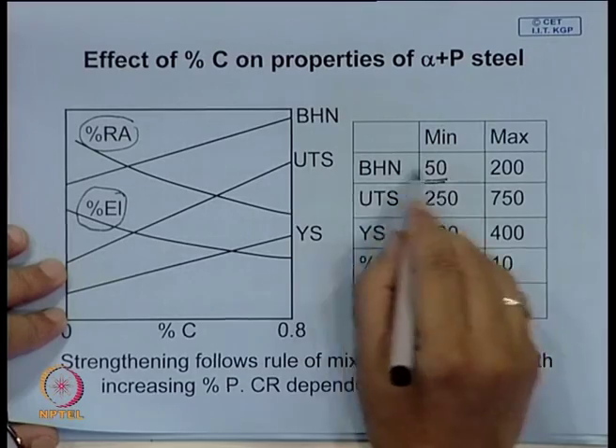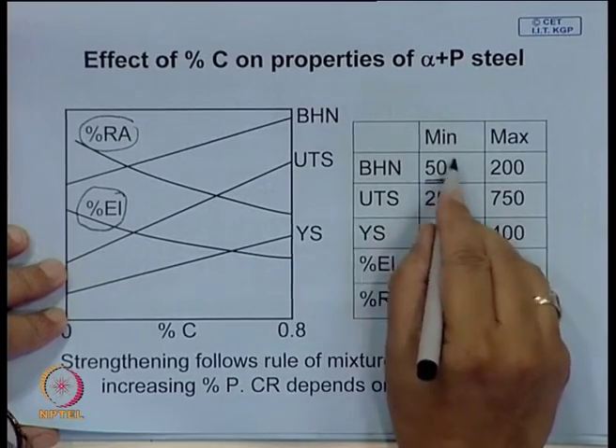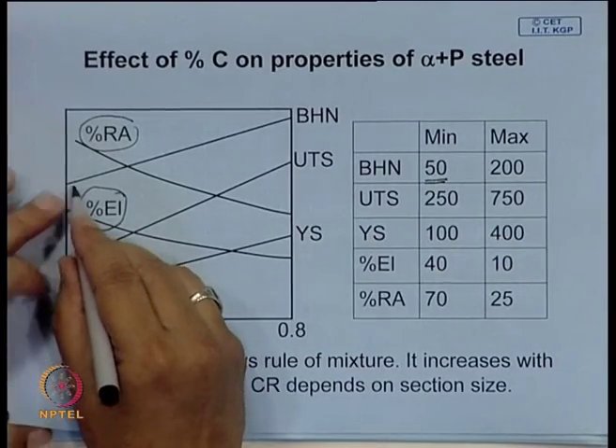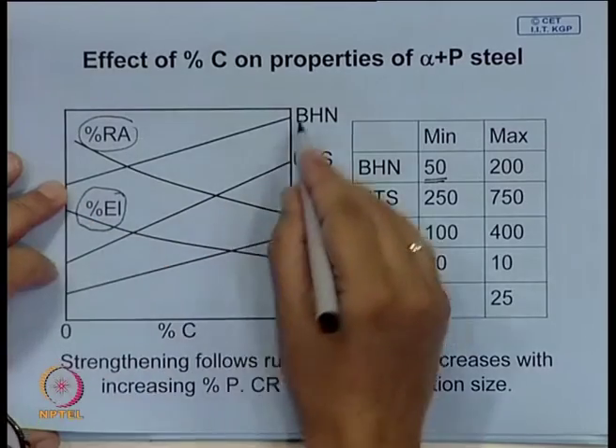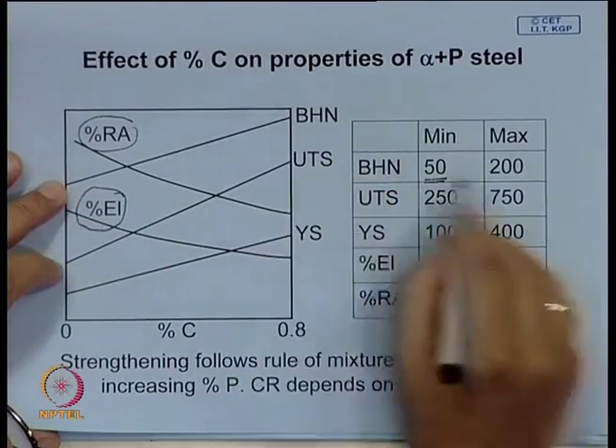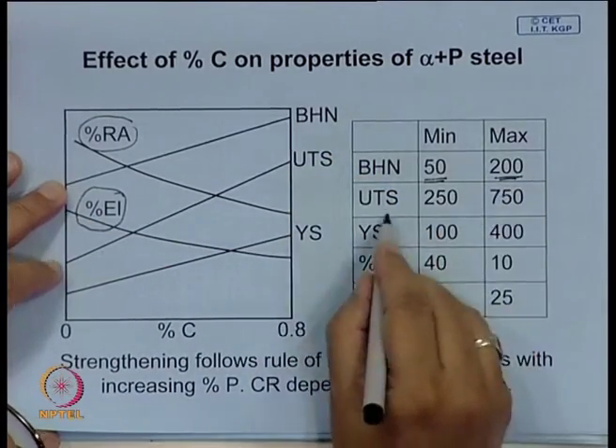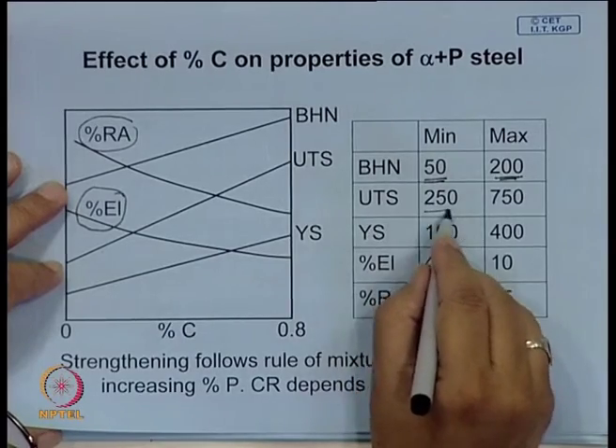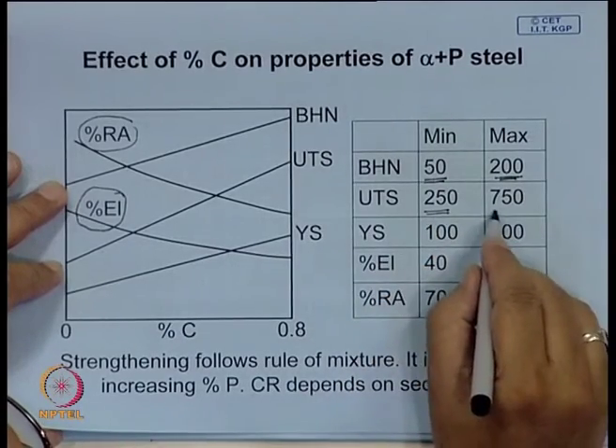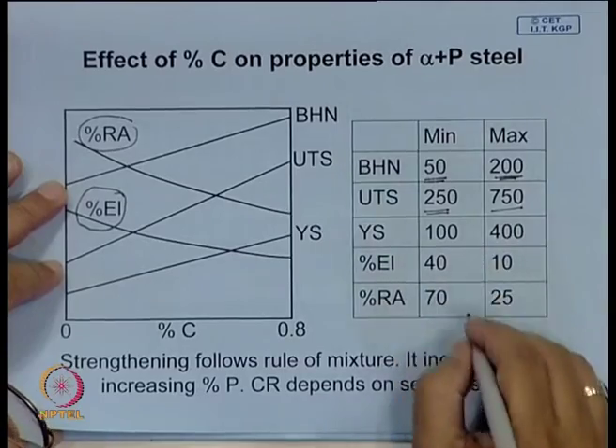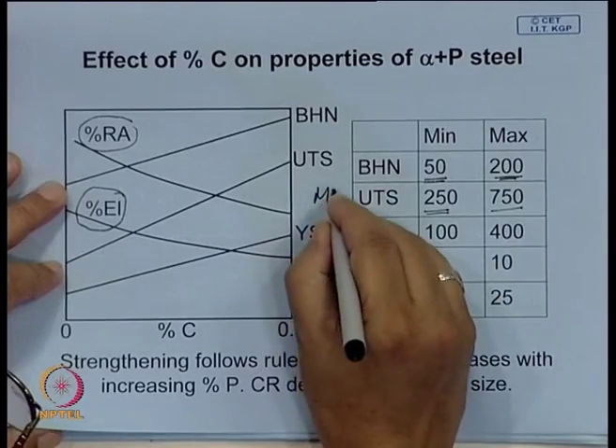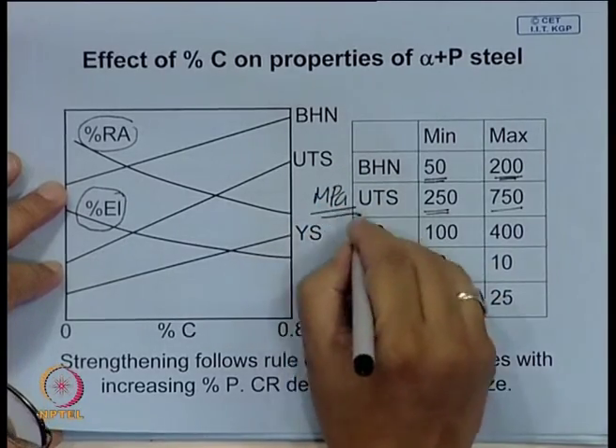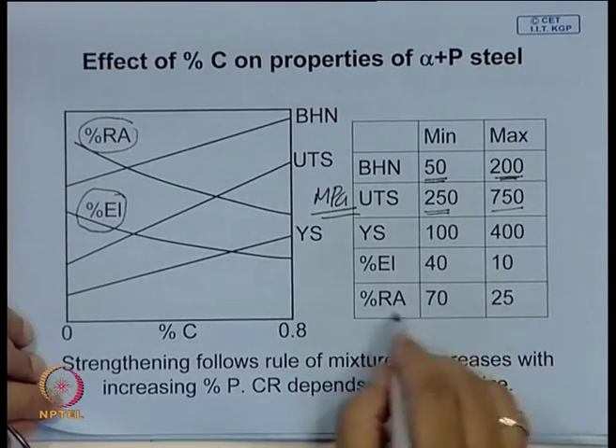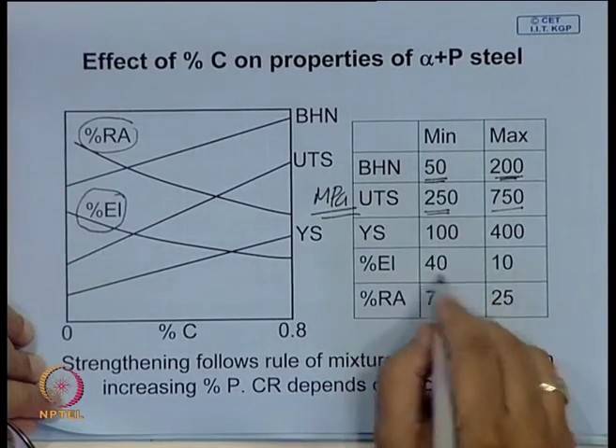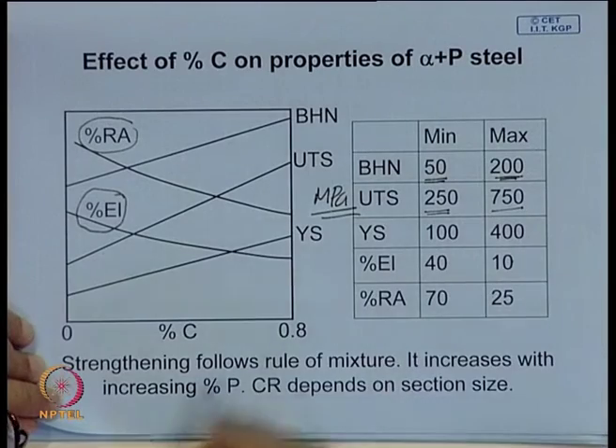The Brinell hardness number is at its minimum particularly when you have virtually no carbon, and if you have 0.8 percent carbon, you get something like this. UTS, ultimate tensile strength, is of this order in MPa, megapascals, and similarly there are some values for ductility.